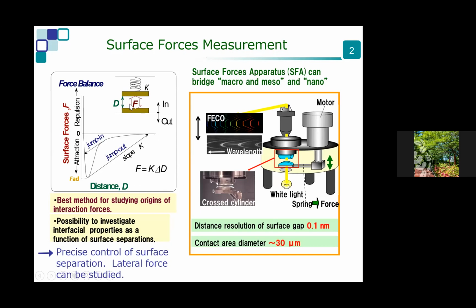We measure interaction force using a spring balance and obtain interaction force profiles, which are interaction potential profiles, so that repulsion is plotted positive and attraction negative, against distance. So we get an interaction profile. This is considered the best method for studying the origin of interaction forces. But often we do not know the origin so clearly.